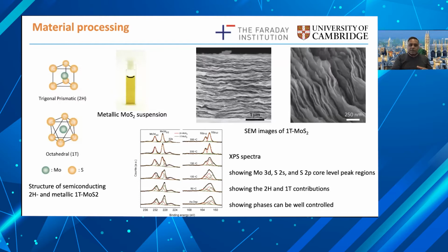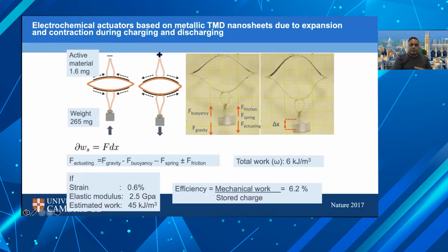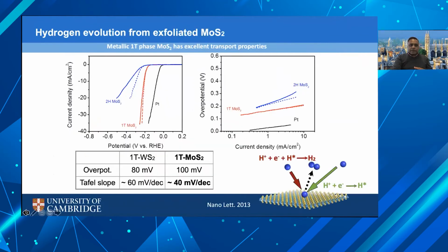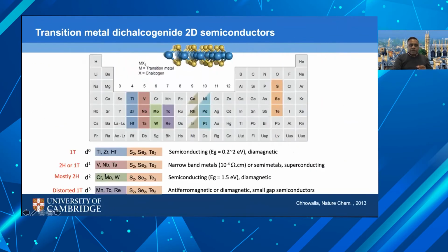If I go all the way back here, niobium disulfide only has one electron. When you have an odd number of electrons in the d orbital, you typically have a stable metallic phase. If you have an even number of electrons in the d orbitals, your TMD compounds tend to be semiconducting. So the 1T and 2H are just different phases, and different materials have different stable and metastable phases. I hope that's clear. Yeah, thank you, Professor Chhowalla. We'll move on to the next question.